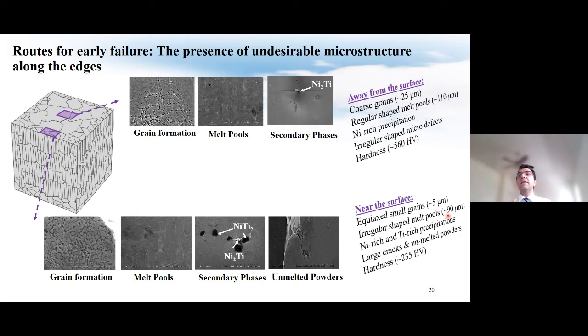We observe significant variation in the microstructure of the specimen when comparing the area near the surface and the area away from the surface. For example, for the area away from the surface, we observe large epitaxial grain, elongated melt pool, and formation of minor brittle phases as well. However, when looking into the area near the surface, we observe refined grain, interconnected melt pools, significant number of brittle precipitates, as well as unmelted powder together with cracks, as you can see here.